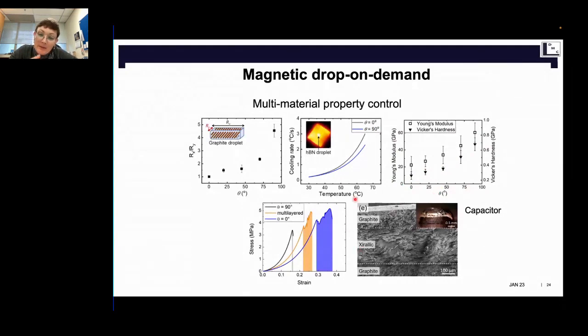If we create multiple angled structures, like this vertical kind of thing, we can also combine or generate new properties. For example, multi-layers in orange will have mechanical properties that are in between the horizontal and the vertical. And so typically we get something that is a lot stiffer, but also a lot tougher than if you have only one orientation. And the last multi-material property control I want to show is we can also combine different materials together to build functional devices like a capacitor. So this is graphite, aluminum oxide, graphite, and we also measured that if you vary the orientation of the middle layer, you vary the capacitance of this capacitor.